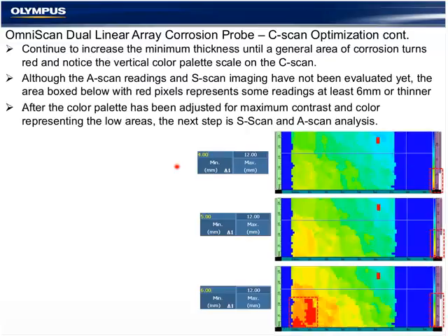I'm going to continue doing that until we see areas of corrosion of severe, either a single area or several areas. As I'm increasing or reducing the color palette range, I'm scaling the color over my thickness as an indication of where trouble spots are. This might be an isolated pit or something that contaminated the gate. This looks like a more realistic area of corrosion. I'm just doing this on the C-scan first without the benefit of the A and the S scan.